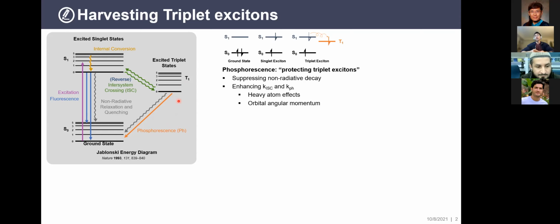So when your lifetime is very long, you need to worry about how to suppress your non-radiative decay, because your emitting process, your radiative decay process, is always competing with your non-radiative decay process, like heat. So how to suppress that, and at the same time, how to enhance your intersystem crossing rate and your phosphorescence emission rate is very important. And people generally use two different strategies. One is the so-called heavy element effect, and the other is how to manage the orbital angular momentum. And this I will explain in the next slide.